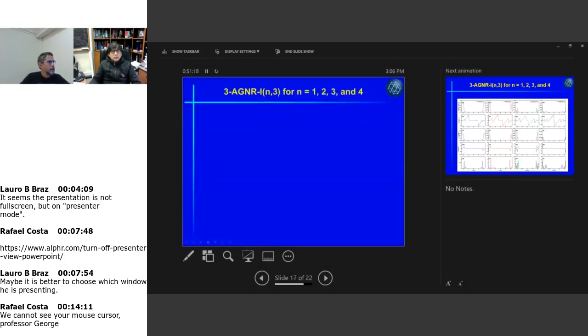Then what we did was we kept capital N equal 3, we kept M equal 3, and then we varied lowercase n from 1, 2, 3, and 4. And the results are these ones here, for n equal 1, n equal 2, n equal 3, n equal 4. And let's go straight to the ZT values here. We get a ZT value equal to 5 here. This is a result that I had showed you already in the previous slide. We put it here just to compare how it changes when we change the value of the parameter n. So we go to a ZT equals 6 here.